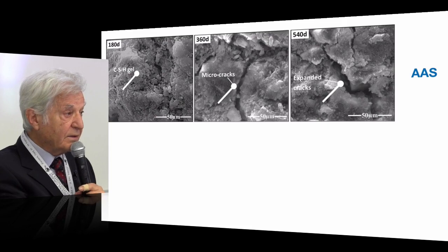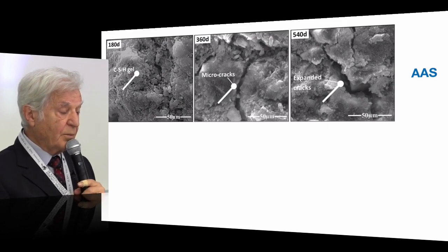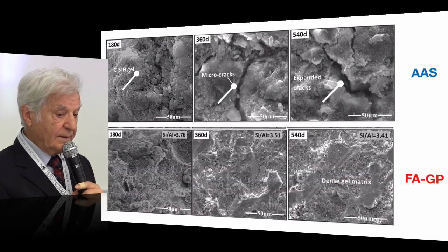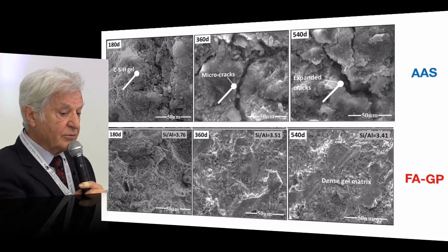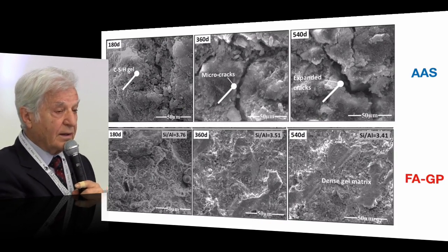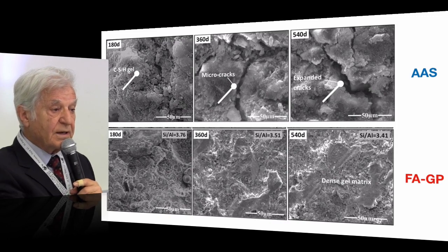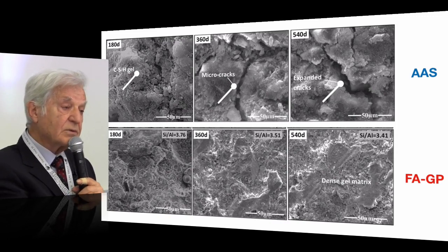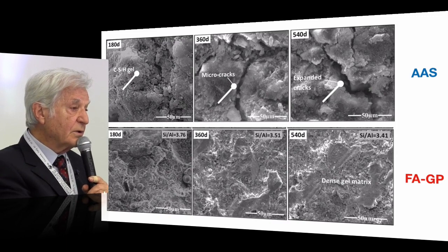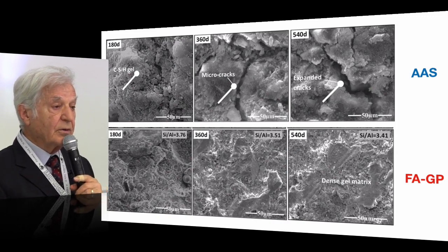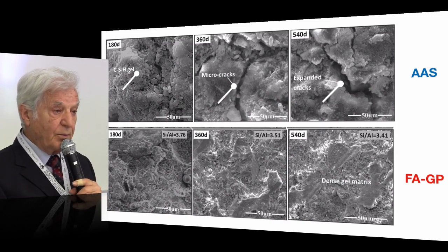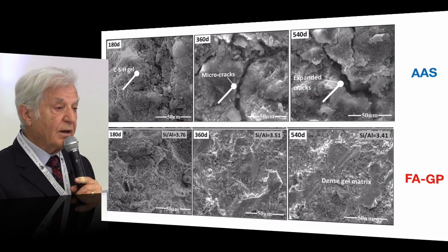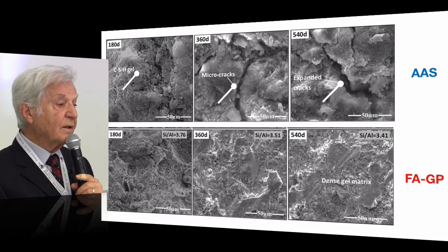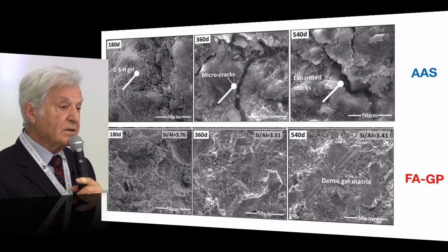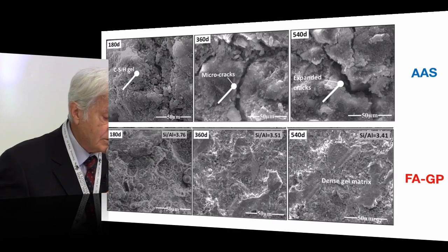This is for alkali activated slag, and for geopolymer fly ash based we have a dense matrix and we have no cracks. So you understand what I claim, and this is the basics of my video series, why alkali activated materials are not geopolymers, that geopolymers are for long-term durability. We don't care about the fact that you have at the beginning a lower strength, but the strength is still enough for applications.